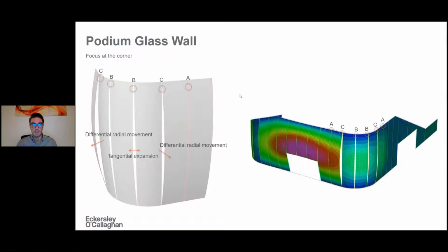Therefore, we had to understand a bit better the behavior and how to cope with these different interfaces that we have. What we did was identify mainly three interfaces. We call the typical one interface A, which is between flat panels, which experience a very similar behavior as the geometry is similar. Then we identified interface B, which is between curved panels. Because of the geometry, the two curved panels will tend to move radially in different directions. Therefore, they will experience mainly tangential expansion when under suction, and the joint between the two glass panels will tend to expand.